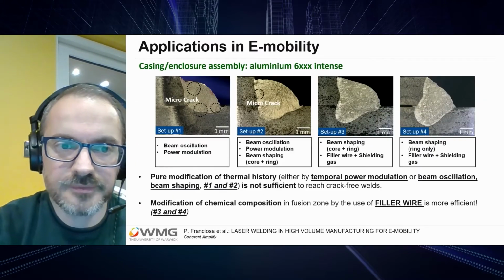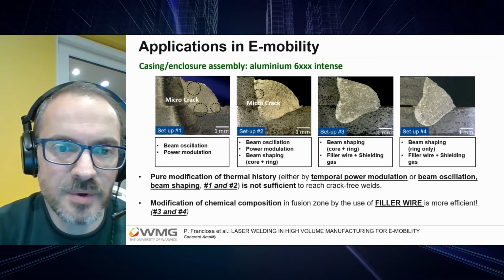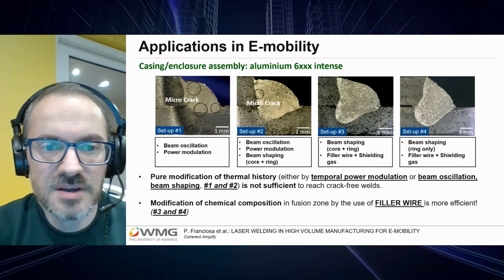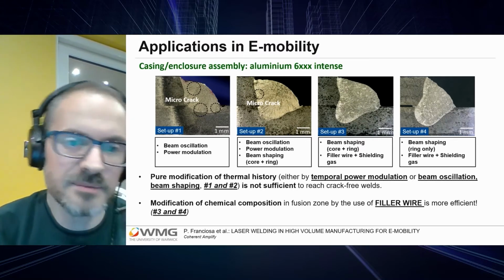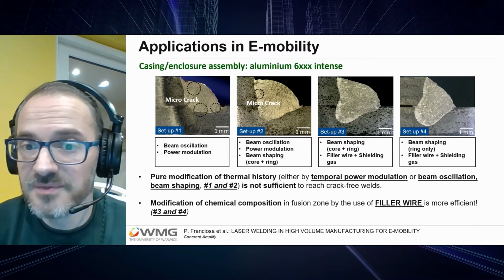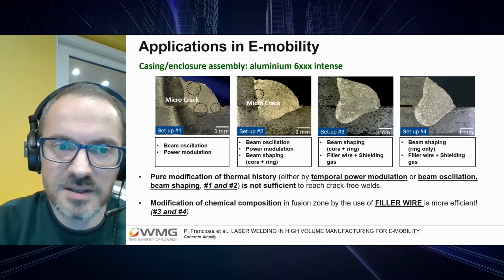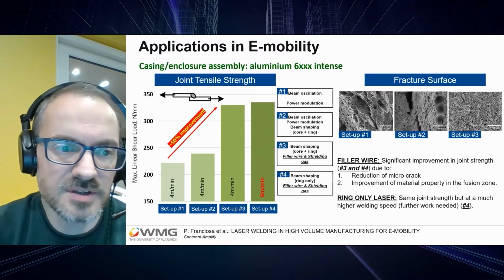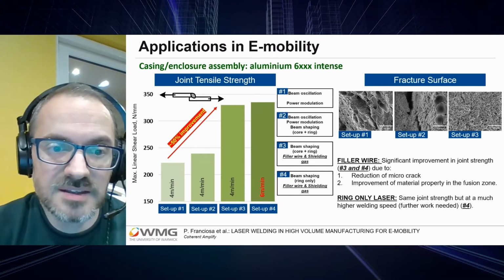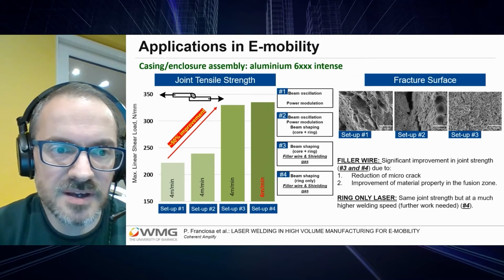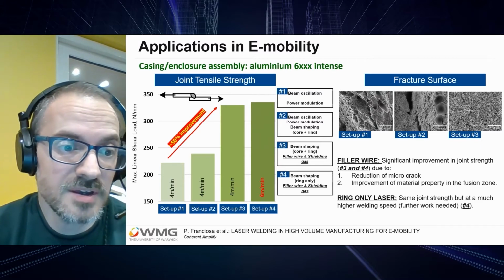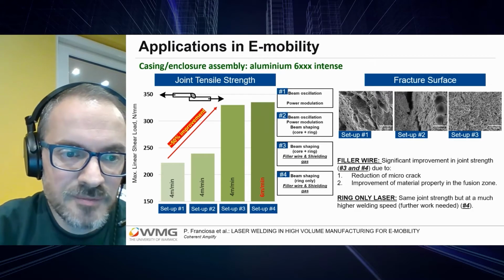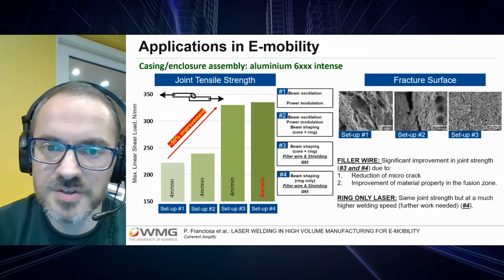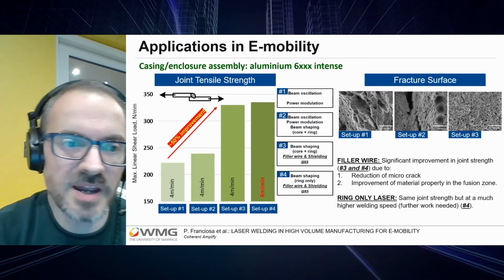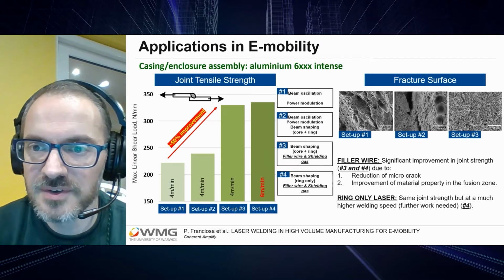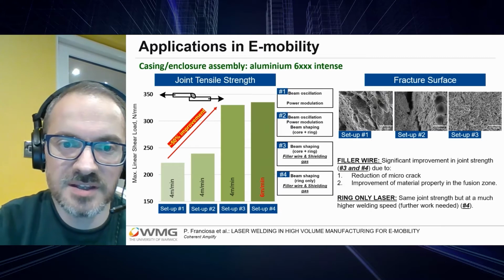We have compared a few different configurations: setup 1, 2, 3, and 4. Setup 1 was beam oscillation and power modulation. Setup 2 was the same as setup 1 but with the core plus ring laser. Setups 3 and 4 were mostly with the filler wire. Now, if we look at the result of the linear lap shear, we see, as expected, that in the case of using the filler wire, the strength of the joint is significantly higher, almost 50% compared to setup 1. However, we also notice some significant improvement between setup 1 and setup 2. So it means the integration of the beam shaping core plus ring reduces the number of micro cracks within the weld.